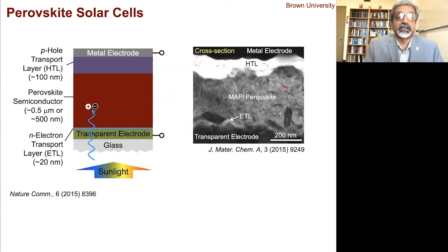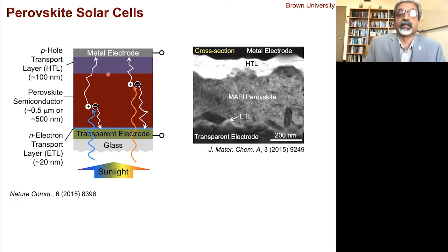So light enters, creates an electron hole pair. The holes go this way, electrons go this way. Deeper into the material, electron hole pairs are generated, holes go on top, electrons go on the bottom. So by the time light has passed through this half micron, it is mostly absorbed and has done its job, which is really tremendous compared to, say, silicon, which takes 200 microns for this to work, right?